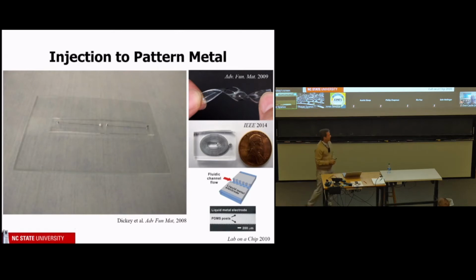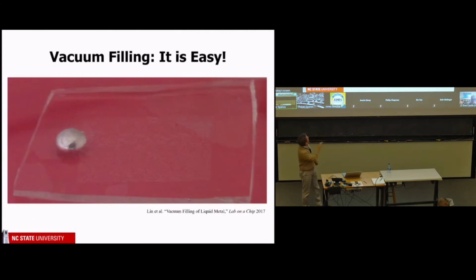And this, we actually have a single inlet, and over that we place the liquid metal. So imagine like an ice cream cone where you put the ice cream on top of the cone. And you can barely faintly see it, but these are microchannels, and there's no outlet hole. But we put this whole thing in a vacuum chamber, which you can't see, and we pull vacuum. Turns out that pulls the air out of these channels, so they're under vacuum.